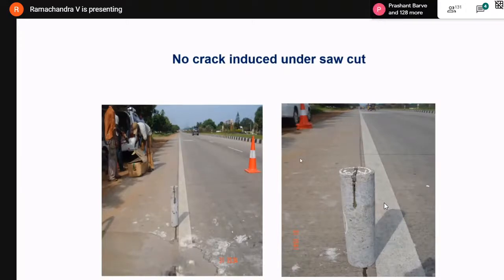At these shoulders, wherever the cut was made at 3.5 plus 3.5, a core was taken, and this was the pattern that the core behaved. Why did it behave like this? We expected cracks to come just below the cores, but the cracks did not come there. Cracks came about 2 meters away from this. This shows that the structural action due to the cutting of these panels was not acting properly. Therefore, what is suggested by IRC, and will come in the next revision of IRC, is that whenever we have these extended shoulders, the cutting should be, first 3.5 is all right, and the next should be 2.5 plus 2.5, that is 5 plus 3.5. Instead of leaving a short paneled edge of 2 meter width, it should be equally spaced. That is the point in case of this longitudinal spacing.